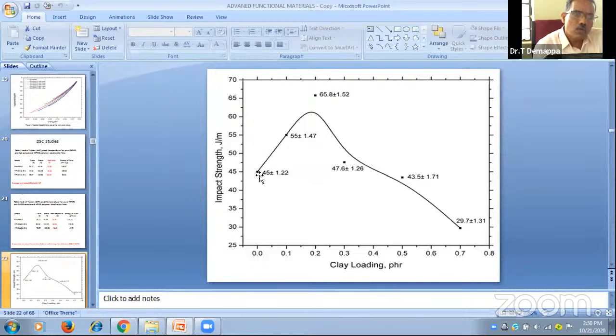Without adding clay, you see, the impact strength is 45 plus or minus 1.22 joules per meter. If you add just 0.1 phr of clay, you see the tremendous increase of impact strength, that is mechanical strength: 55 plus or minus 1.47 joules per meter. At 0.2, the maximum impact strength is found to be 65.8 plus or minus 1.52 joules per meter. Then 0.3 decreases, 0.4 decreases, still 0.7 decreases.